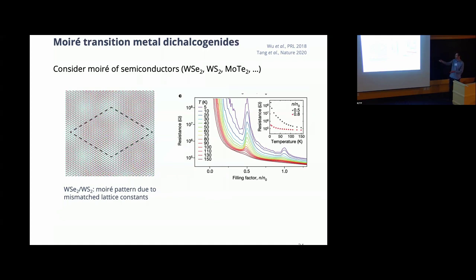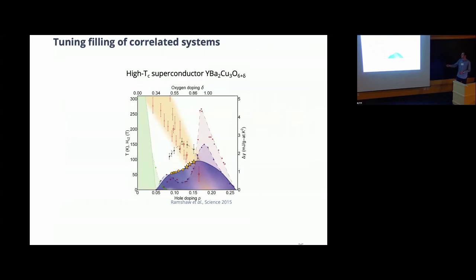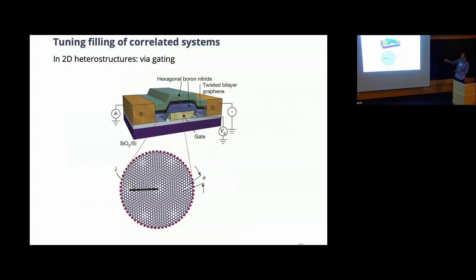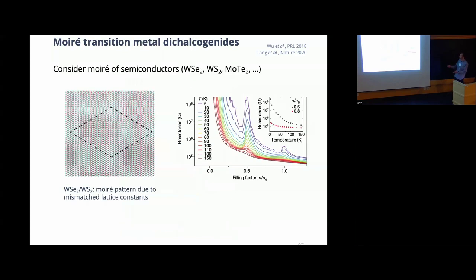This is a quite remarkable plot already for us in condensed matter physics, because usually if we plot these phase diagrams where we plot the filling of the system, we rather get plots like this, where you have a few dots. This is just reflecting the fact that very often to tune the number of electrons in a sample, ordinarily, you need to grow a new sample. So you typically need to change the chemical composition, and you need to follow a very complicated procedure to actually get a new material. But here in these systems, you can just tune the filling of this material by basically applying a perpendicular gate voltage. So this is an extremely easy thing to do, and you can do this with very high precision. So this gives you this beautiful curve rather than just a few scattered dots.